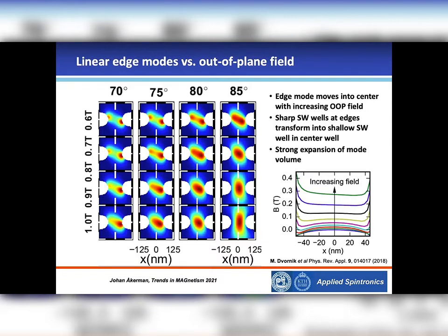And we do that by applying a magnetic field with an out-of-plane angle, almost 90 degrees, and relatively strong. So in this case, the material is nickel iron. To get any effect, to get any angle of the nickel iron out of plane, you need to apply roughly a large fraction of the saturation magnetization, which is about 1 Tesla.